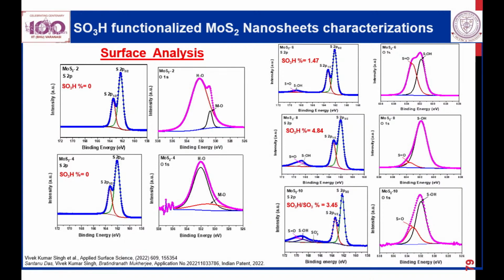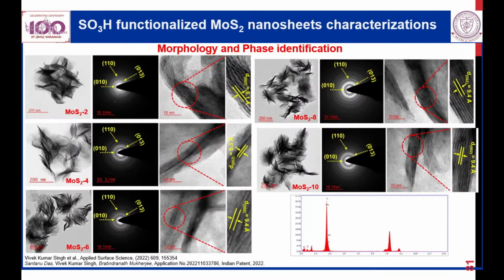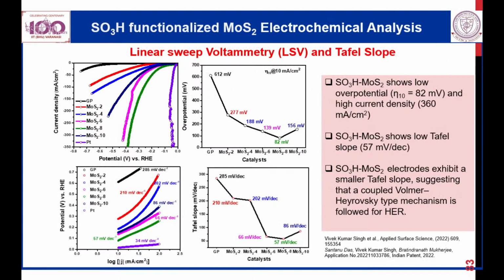How did we find this intercalation? We found it with HRTEM. If we look at HRTEM, the interlayer spacing increases from 6.1 to 9.4. That's really vast and big. So if you see that increase of the interlayer structure and the sulfonated molecules going inside of it, that's what is giving a lot of improvement in catalytic sites on its surface.